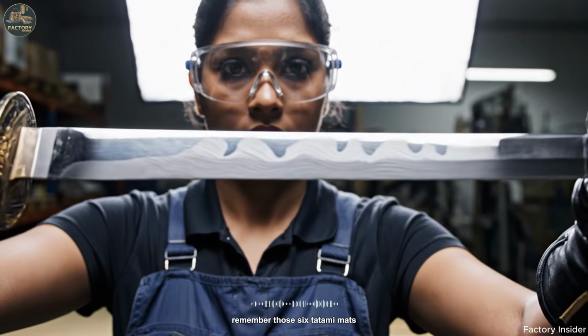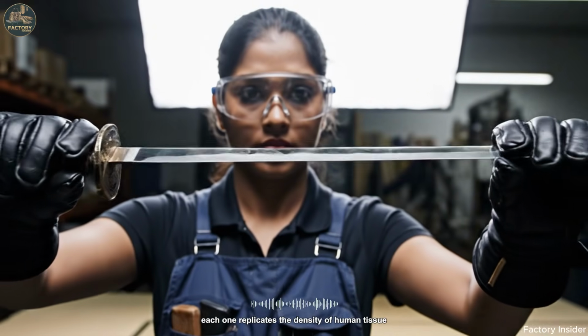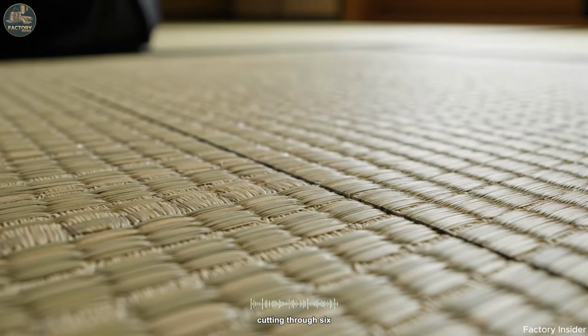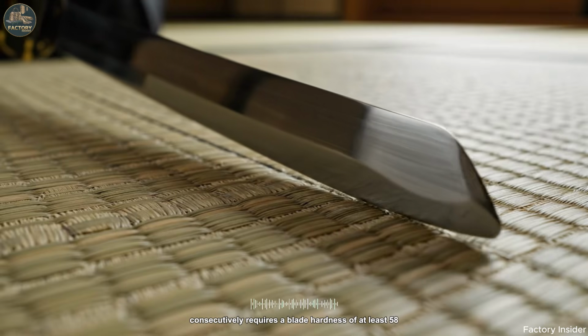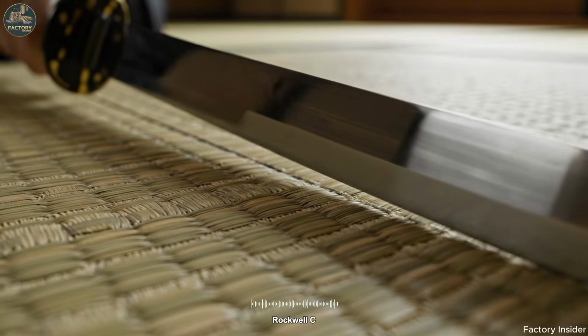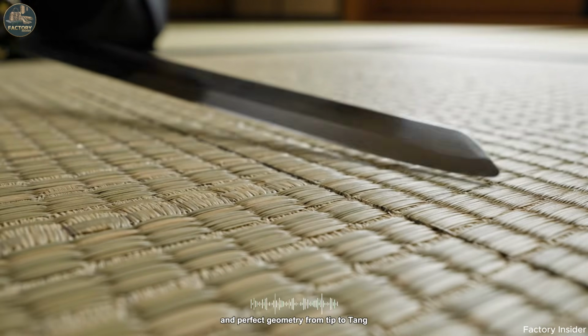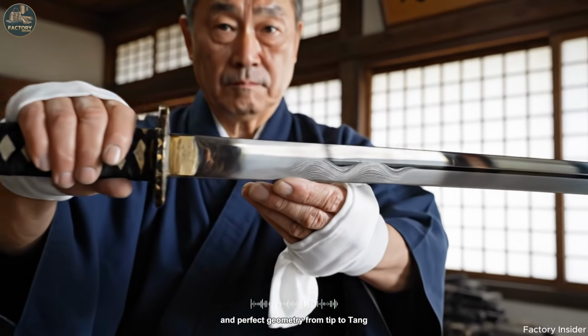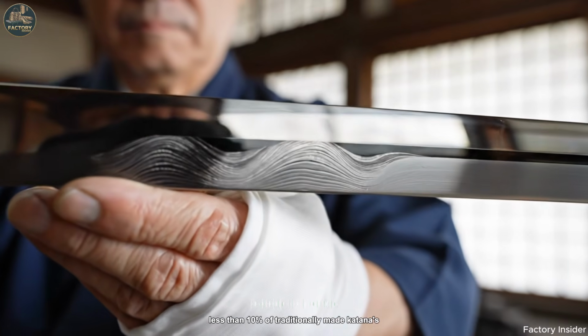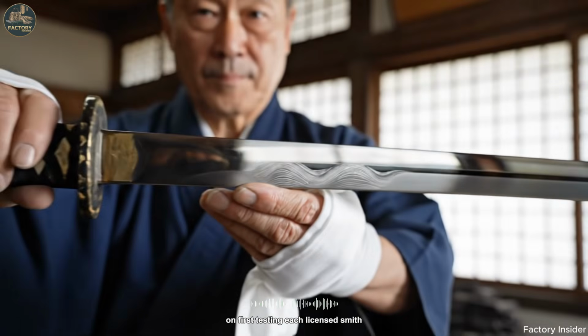Remember those 6 tatami mats from the opening? Each one replicates the density of human tissue. Cutting through 6 consecutively requires a blade hardness of at least 58 Rockwell C, an edge angle under 20 degrees, and perfect geometry from tip to tang. Less than 10% of traditionally made katanas achieve this level of performance on first testing.